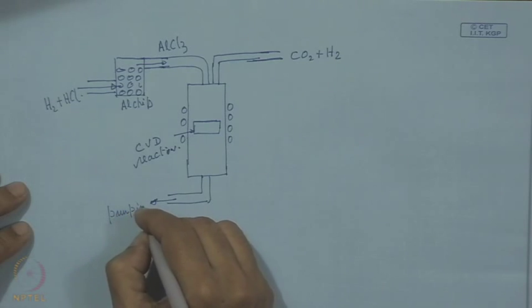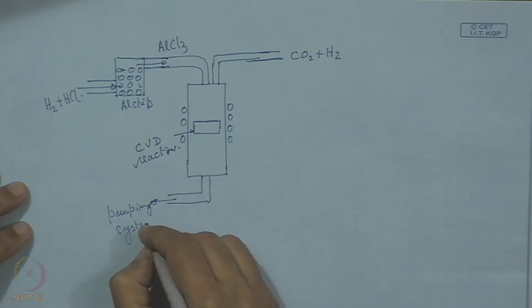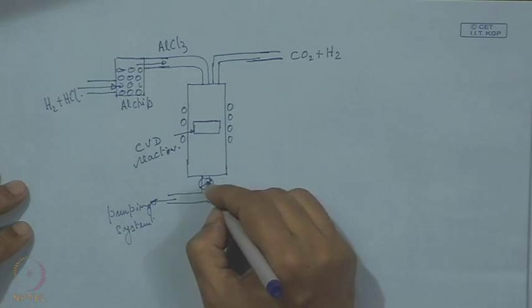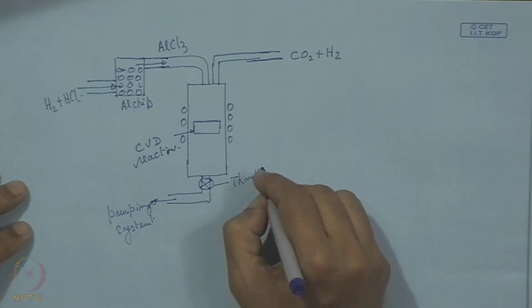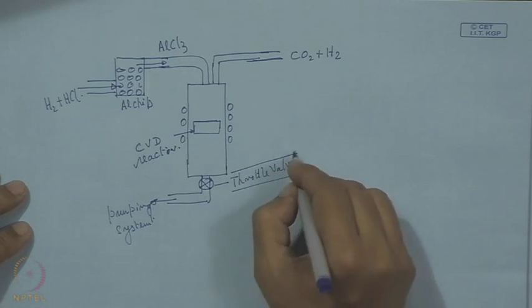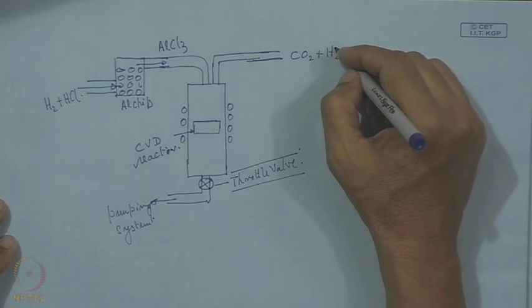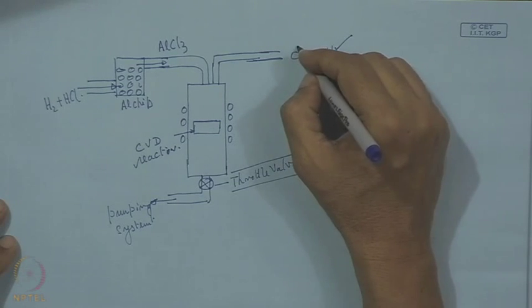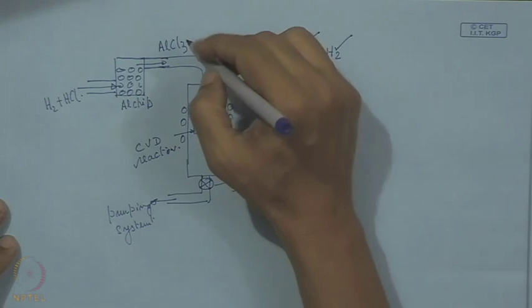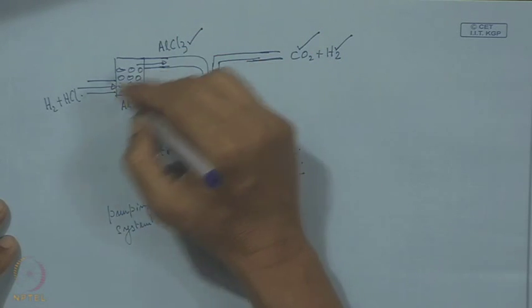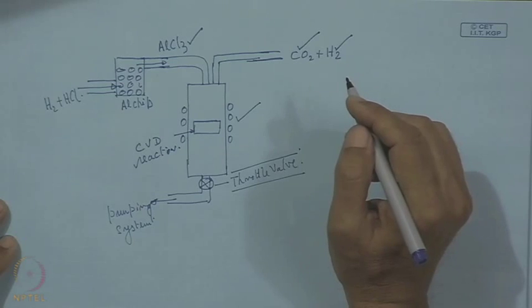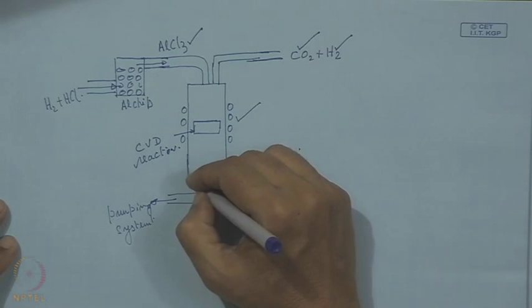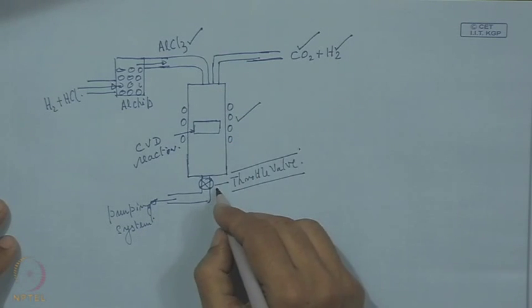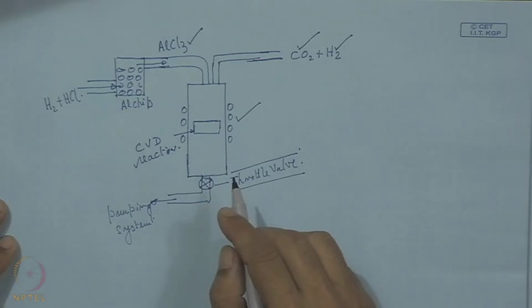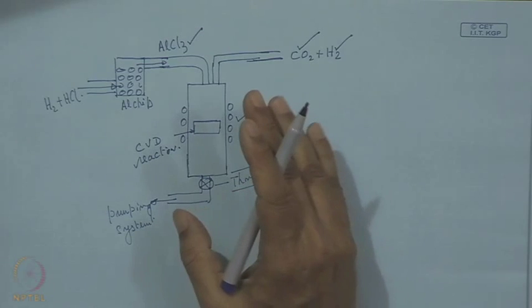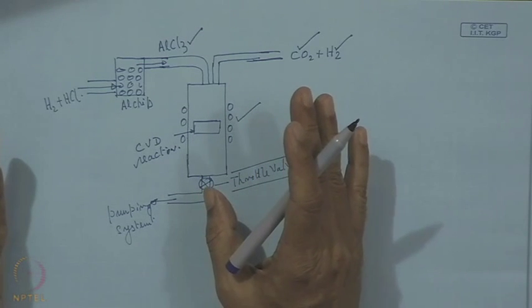So, this is actually the pumping system, and here on the downstream side there is a throttle valve for controlling the system pressure. So, the partial pressure of hydrogen, partial pressure of CO2, partial pressure of AlCl3, which is saturated with hydrogen, then the temperature inside the CVD reactor, and the total pressure prevailing inside the chamber, that is controlled by this throttle valve. So, this is basically the CVD principle which is practiced in this particular CVD chamber.